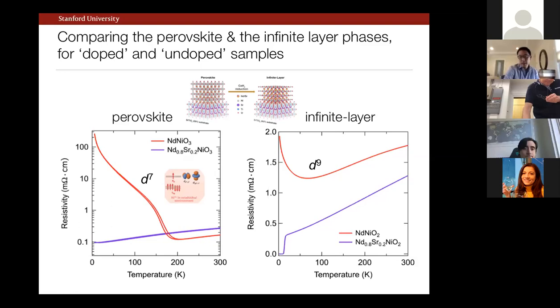Now, if we reduce these compounds into the infinite layer form, so NdNiO2, the undoped case, you can see here in red, has a weak insulating upturn. Of course, there are still many open questions about this, but I should emphasize that this is not a good insulator. This is definitely not what you would see for the undoped cuprates, where the transport gap would be much, much larger. As far as the doped case, what you see is indeed a nice superconducting transition. And again, the characteristic scale for, let's say, the room temperature resistivity that's relevant here is about 1 milliohm centimeter. I'll make a few comments more on that as we go on.